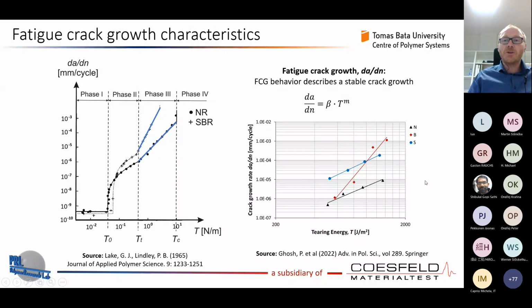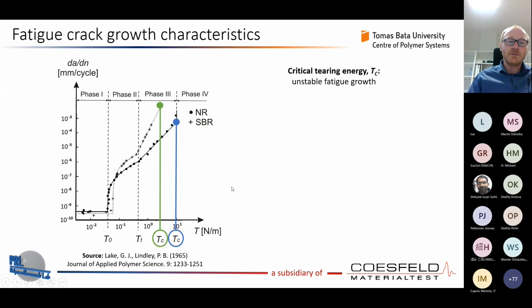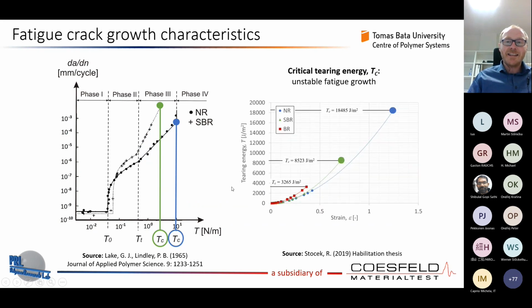Very exactly corresponding, and as you can see, using a different machine, there is always the same result for these materials, corresponding even with Lake and Lindley. And then we have the last point, which is the TC, and what we measured as well with another method is that natural rubber has the highest TC, then styrene butadiene rubber, corresponding again with Lake and Lindley, and the lowest TC has butadiene rubber, exactly as expected by all of you. So this nicely corresponds, and we can really find everything about the rubber fracture behavior within this diagram.